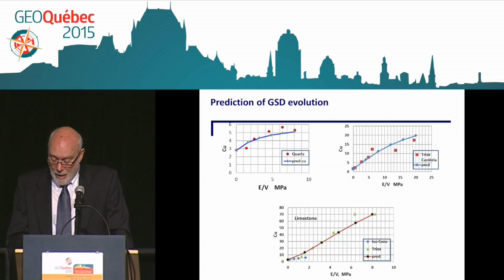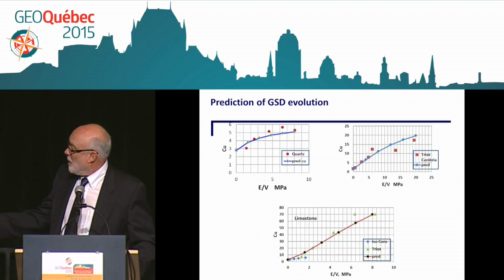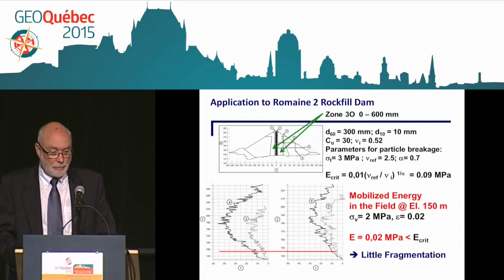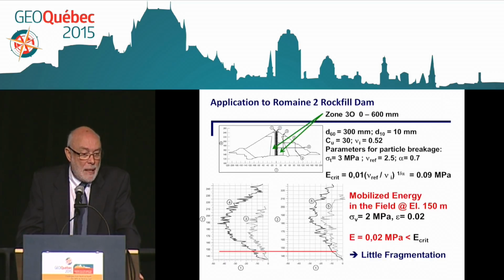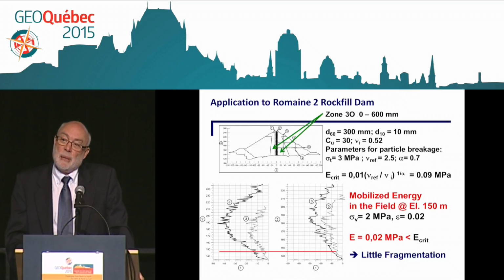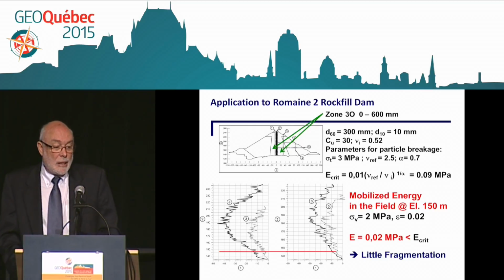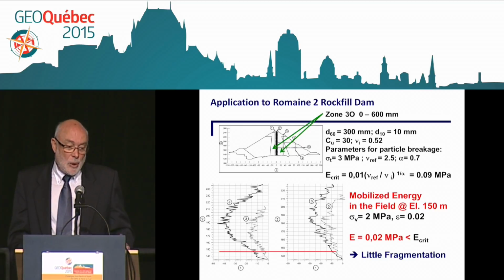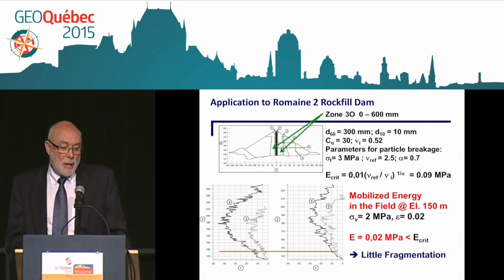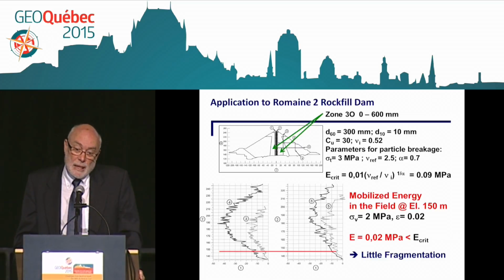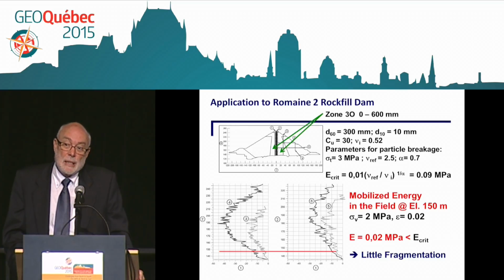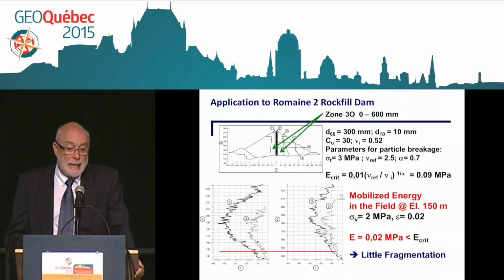Now, our goal is to see where we would stop depending on the situation in the field. This is what I'm going to propose to you right now, how to apply it to Romaine 2. We have a zone 3.0, that is a 0-600 millimeter rock fill. The parameters tell us that the critical energy would be 0.09 megapascal. And when we look at the deformation data during construction, we see that at the lowest level, where the highest stresses are, we have mobilized only 0.02 megapascal of input energy during the placement of the rock fill. Hence, we can conclude from this study that we will get very little fragmentation in situ, and hence we should not expect very important settlement.